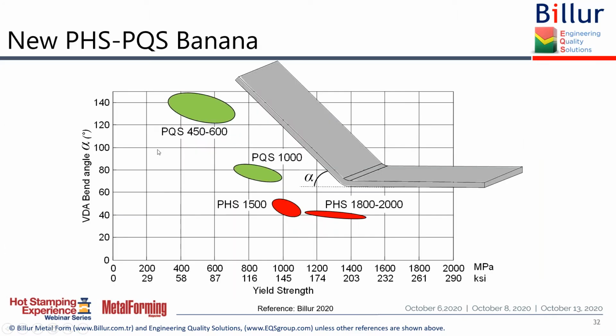And now, instead of the famous banana, here's a new banana curve. I put the yield strength, and as you will see, it's from 950 to about 1200. And then we have the new grades, and PQS 1000 has almost similar yield strength, and it can be bent to about 1.5 times larger angle. And PQS grades, by the way, are like 2 or 3 times more bendable than the PHS 1500s.